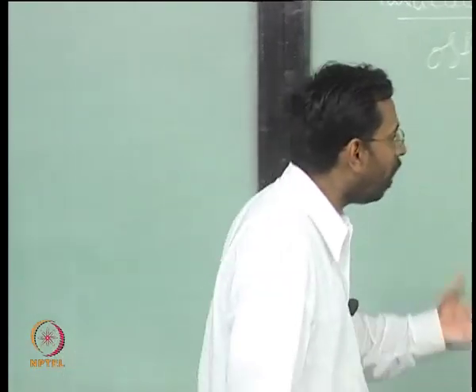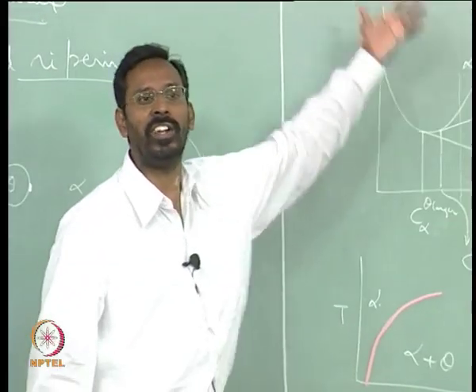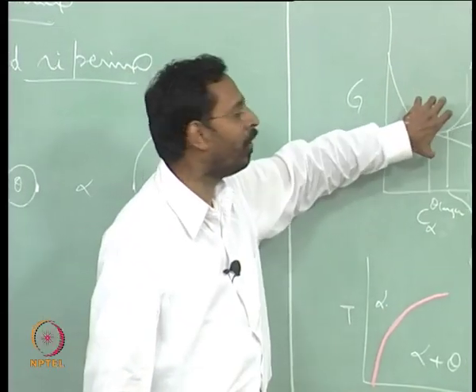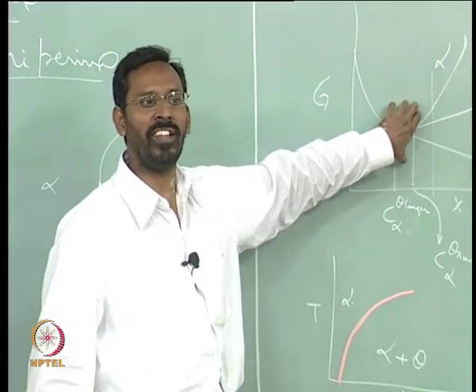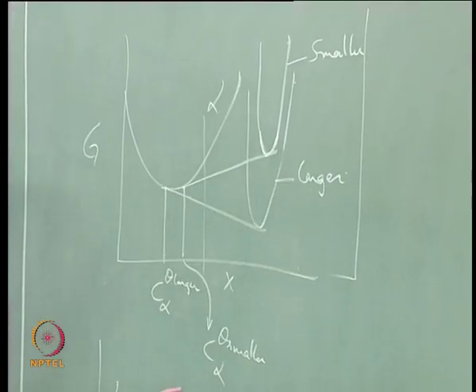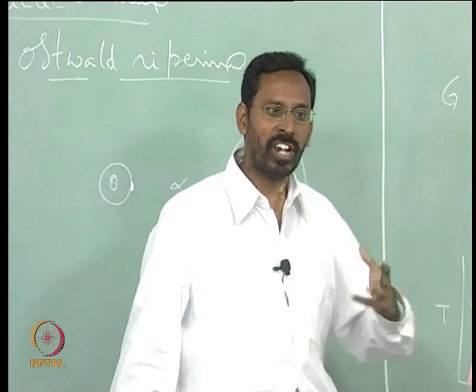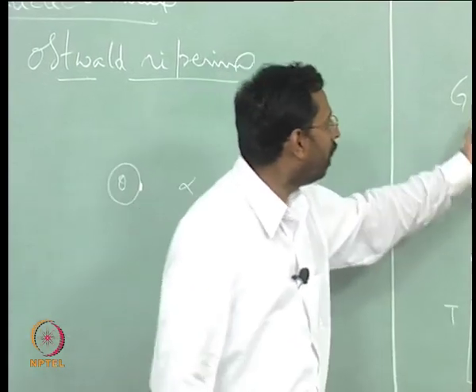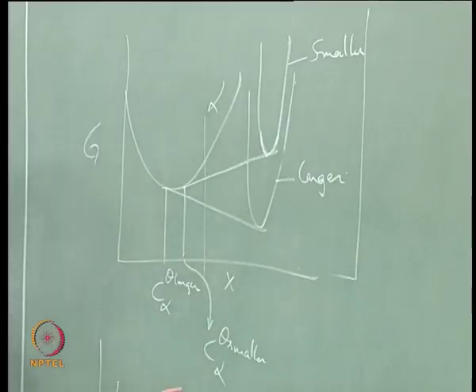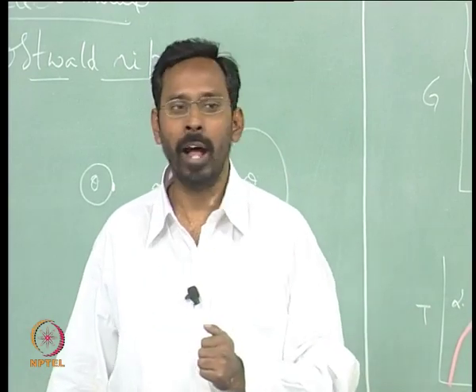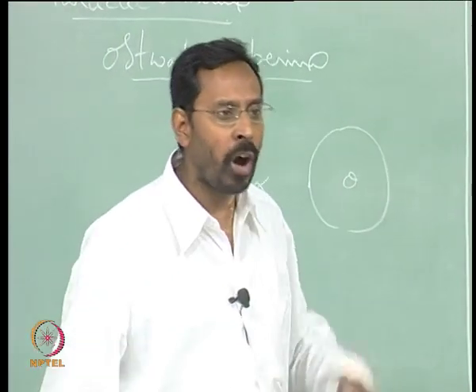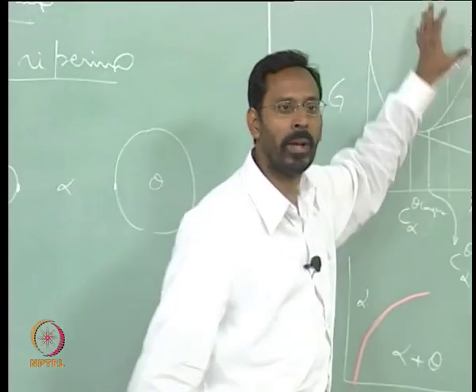The moment you bring in size effects, this is what we call size effects, then you will start seeing that the free energies start shifting. The alpha also, instead of an alpha of a very large grain size, if I now start looking at nano grained alpha trying to precipitate out of the theta, then the alpha free energy curve also will shift. So, nano grained alpha will definitely have a higher free energy with respect to an alpha of a much larger grain size. So, all those things are what we call size effects.